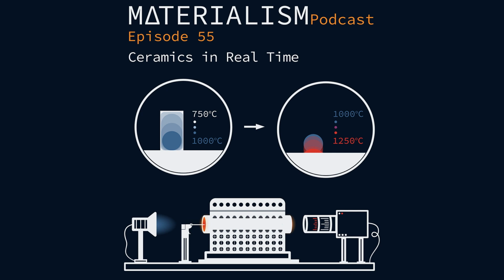Of course, this is not good for something that sinters 10%, because it always goes out of the field of view. So the idea was to motorize the camera, first one and then both motorized. With motorized camera and the software controlling them, as the sample is going to exit from the field of view, the analysis is frozen for a few milliseconds. The camera moves, brings back the image in the center of the camera, and then the analysis is resumed and it goes on from that point till potentially zero. You can follow everything. So that was the core innovation in that instrument, which of course is very useful for ceramics, for soft material, for incoherent material. We measured sand. I mean, you can press together some sand and measure.